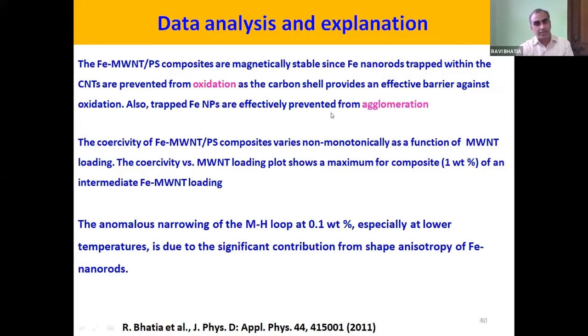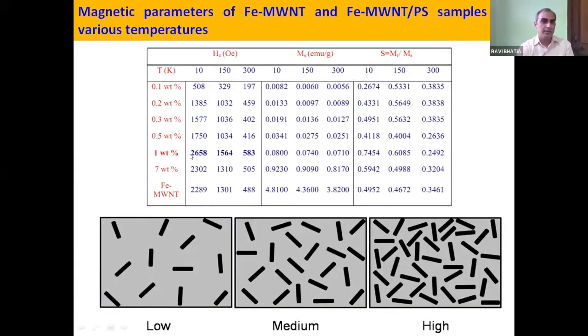Coercivity of these samples varies non-monotonically as a function of CNT loading, where the 1 weight % sample exhibits the maximum coercivity of the order of 2.7 kilo Oersted. Here you just look at the number, 2658 Oersted. We can say 2.7 kilo Oersted at the lowest temperature. There is a wonderful thing to share here: bulk iron particle exhibits the highest value of magnetization of 220 EMU per gram, and its coercivity is 1 Oersted, and these two data are from room temperature measurement.